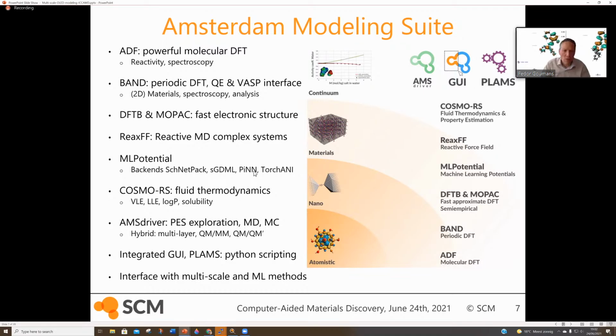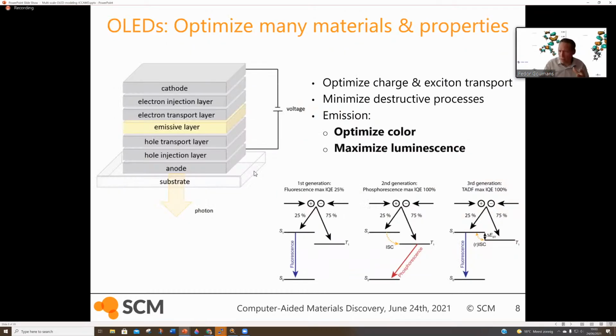And so the first generation of these OLED emitters were classical fluorescent emitters. So an electron and a hole would meet, they would form an exciton, so an excited state where we have two charges being localized on different units. And that excitonic state could then internally convert into a singlet excited state on the emitter, and that could fluoresce, emit a photon to the ground state. But in 25% of the cases, because of spin statistics, so there's only one singlet state and there's three triplet states when you have two spin-half particles, a hole and an electron, meet, 75% of the energy that you put into it would end up in a triplet state, and that triplet state would be non-radiative because